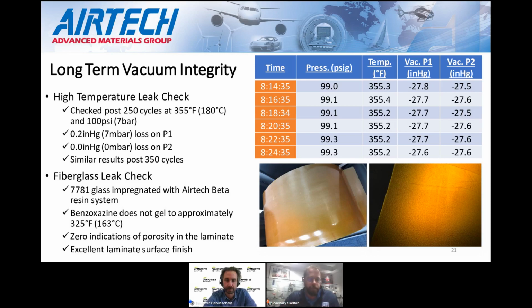So we took some 7781 glass, very thin fiberglass, and then our own Airtech beta resin system, a benzoxazine resin system. Traditionally, they're done with epoxies. We chose to do the benzoxazine just due to the very high gel point, so we wanted to capture as broad of a processing window as possible. And as you can see in the laminate there, there's zero indications of any porosity, excellent surface finish. So the idea is you can hold it up to the light. If you had a leak, there'd be kind of like a starburst pattern coming from where that leak is.